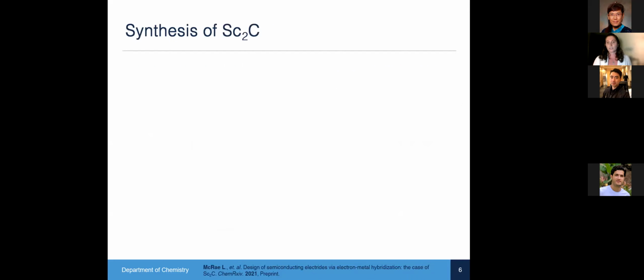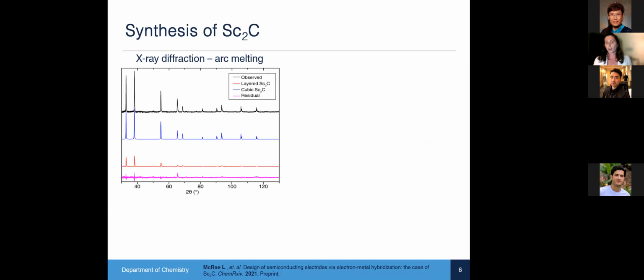So we set out to do this synthesis by combining scandium metal and graphite in an arc melter. And then after arc melting, we took an X-ray diffraction pattern and compared it to our predicted phases. You can see in the diffraction pattern, we have degrees on the x-axis, and intensities on the y-axis. At 50 degrees 2 theta in the layered phase, even though it's very similar to the cubic diffraction pattern, we have a peak that is distinct to just that phase.